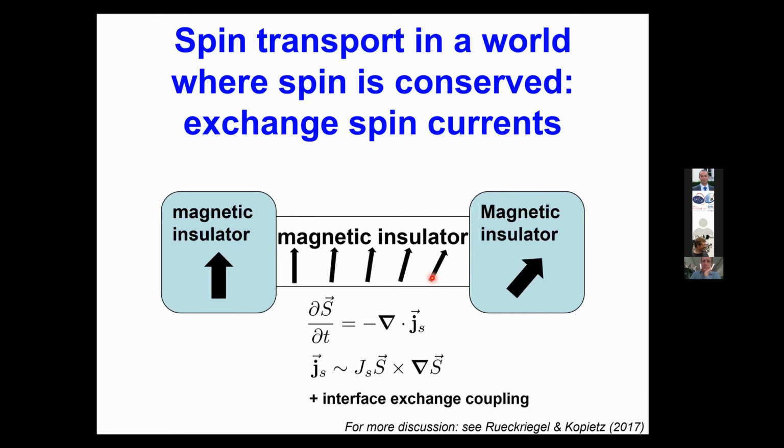There should be some loophole in this reasoning, but what could indeed hinder this kind of naive experiment? Once again, rotate the magnetic field at the left end, and the signal would be transferred to the right end, because mathematically it's indeed identical. I think it would actually work. So I think even for the ferromagnet, it would work with easy plane anisotropy up to some point, because in an easy plane ferromagnet, the spectrum is actually linear also in the symmetry broken phase, if your anisotropy is stronger than the external field, say.